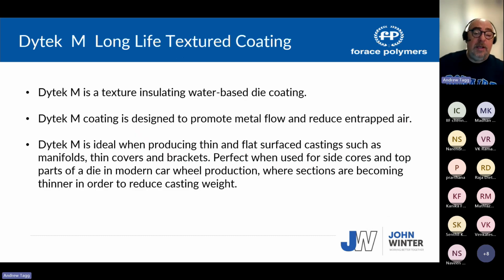Dytek M is a coating specifically designed, it's very textured, for thin section castings. When you've got a thin section casting, because the aluminium forms a strong meniscus, if you have too smooth a coating, 2 things happen. You can get entrapment of air, or you're not breaking the oxide film as the metal flows. So a smooth coating will impair the ability of the aluminium to flow. So for flat surfaces or surfaces of very thin section, you need a specific texture coating.